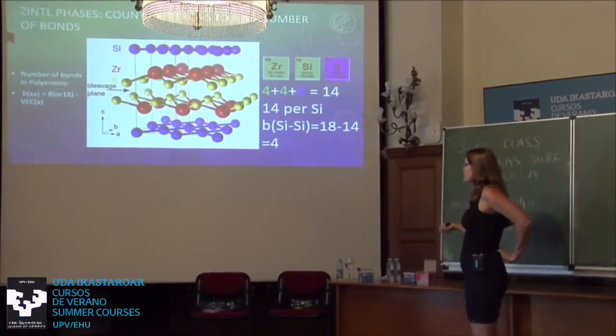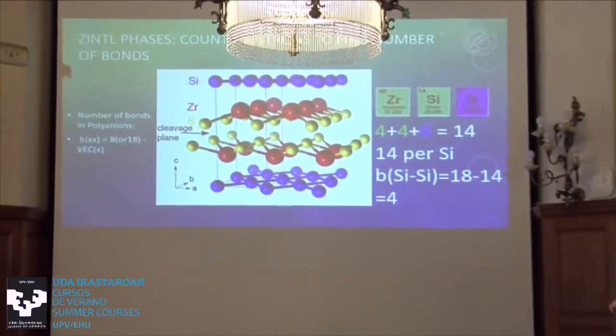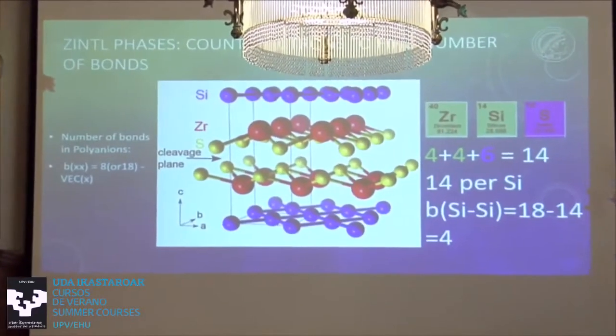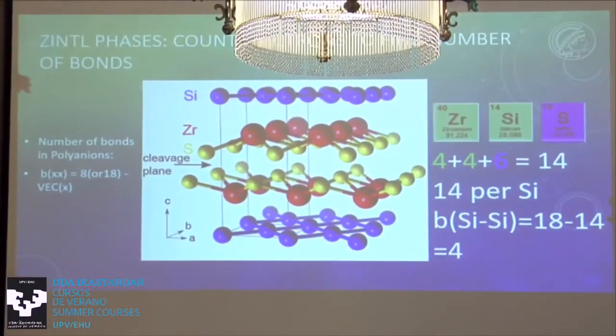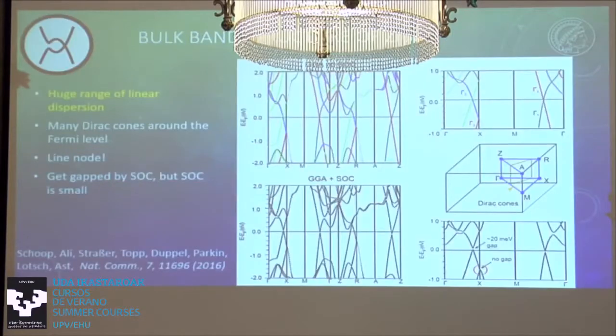And then I already mentioned this before. This is a charge balance material. If you take into account the Zintl concept and the bonding, it could be a perfect 3D Dirac semi-metal just by chemical reasons. So I went ahead and did the DFT and looked at the band structure, and I found not only does it have Dirac crossings, it also has some with a very, very large energy dispersion. So that's the last point I wanted to improve from 3D Dirac semi-metals, and it's also given here.